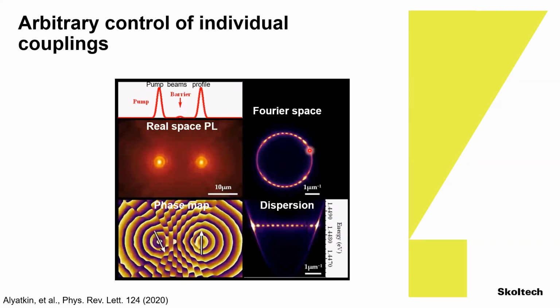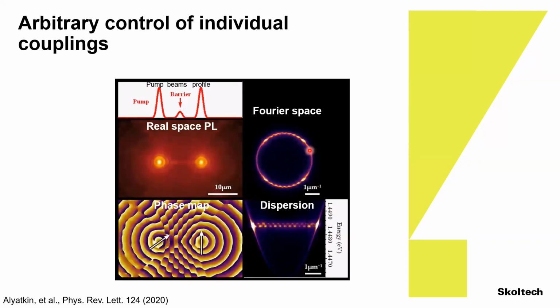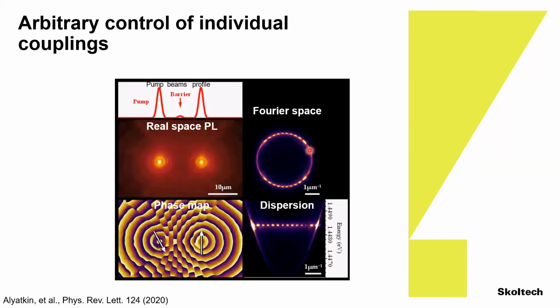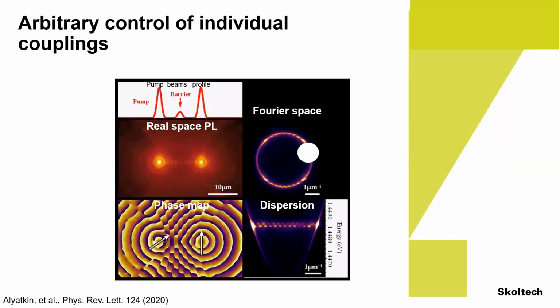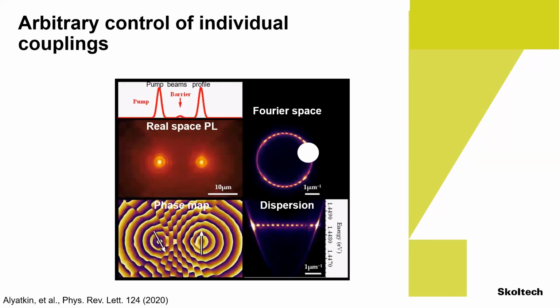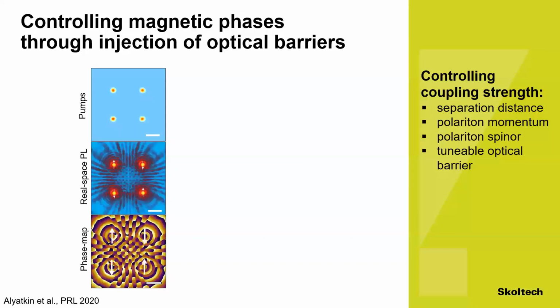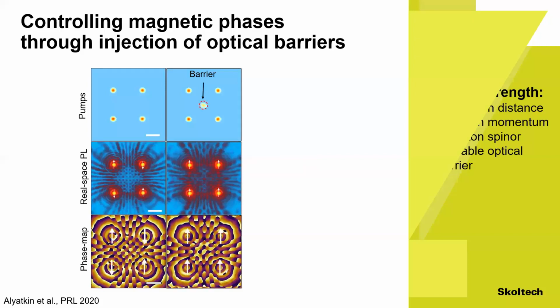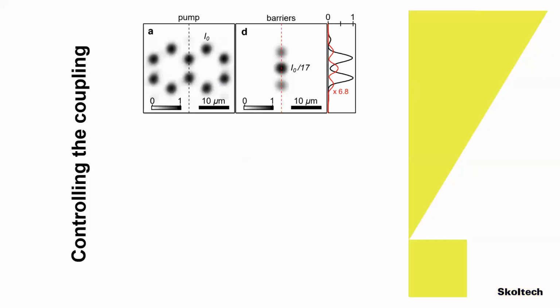Now let's do the same thing with the vortices. We also did it for lattices, and we could play between different magnetic phases in frustration for condensates. Let's go to the vortices. If I have two of these rings, the condensates, with the quantum vortices occurring between, I will create a barrier, which I will put exactly here. And with the amplitude of the barrier, which is not just one spot, it's a bit more complicated now, I will be looking if I first of all have vortices. It looks like I do. Without barrier, two vortices, and with barriers, again, two vortices.